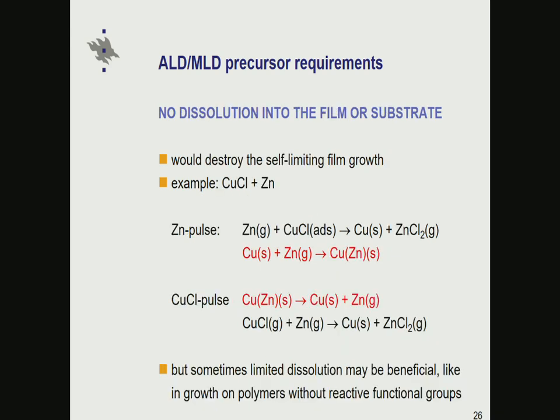Sometimes we have also observed problems where there is a dissolution of the precursors into the films, which can destroy the self-limiting growth quite completely. This happened in our first attempts to deposit copper by ALD. We used copper chloride and zinc. Originally it works pretty nicely: once we have copper chloride adsorbed on the surface, we bring in zinc, and this textbook redox reaction takes place, so that copper is reduced and zinc is oxidized, producing zinc chloride and metallic copper.